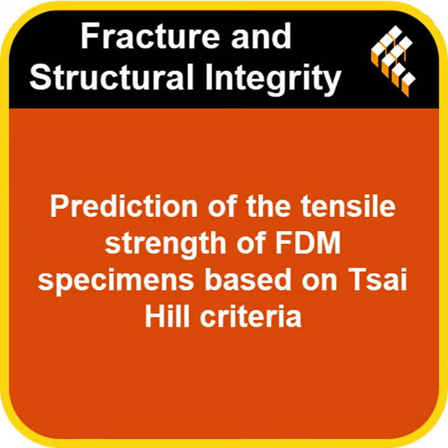The study really emphasized that the contour significantly enhanced the shear strength and toughness across most of the orientations they looked at. Good to know. They did mention, as a side note, that getting good DIC images for all the shear specimens was a bit challenging, maybe due to the complex deformation or image quality. Right. But the overall trends in terms of strength and failure modes were pretty clear from the mechanical testing data. Okay, so we've got a good handle now on how these PETG parts behave under pull and shear based on how they're printed. Now, let's circle back to that engineering model you mentioned earlier, the Tsai Hill failure criterion.